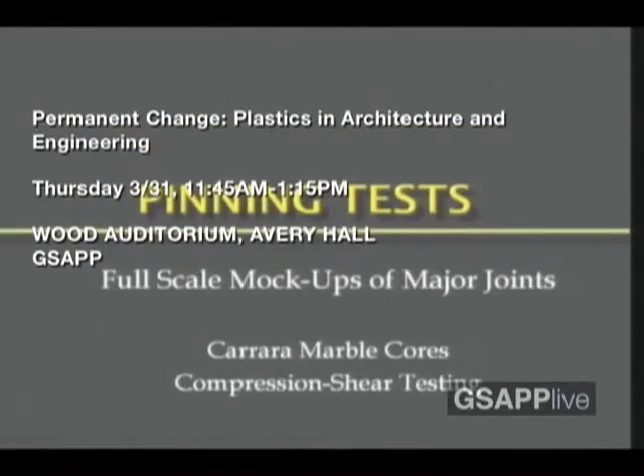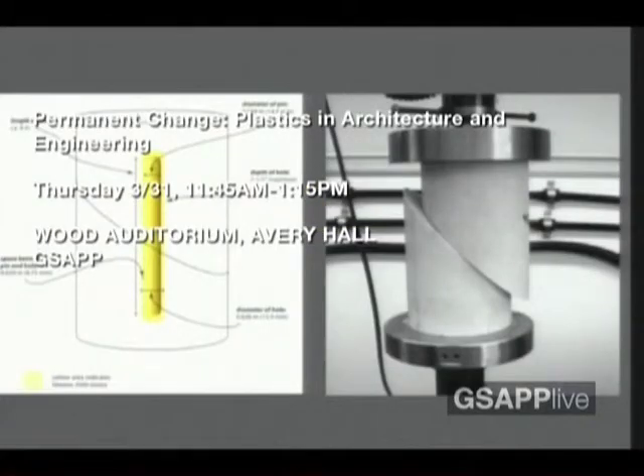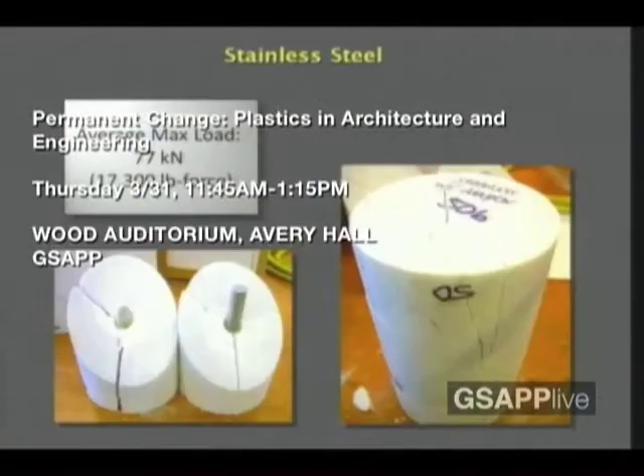So one of the things we then did is make some full-scale mock-ups of all these broken joints and then press them to failure and see what kind of results we get. So we actually took large marble cores, mimicking the breaks in some of the joints, these shear joints, glued them with the different pinning materials, and then pressed them to failure. And if you do that with stainless steel, this is what you get. You actually destroy the marble sculpture in the process of a catastrophic failure of the system. This is exactly against the typical principles of conservation, where the repair is supposed to fail and not the parent material.